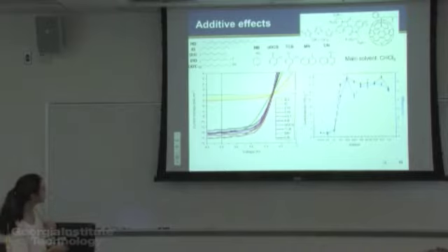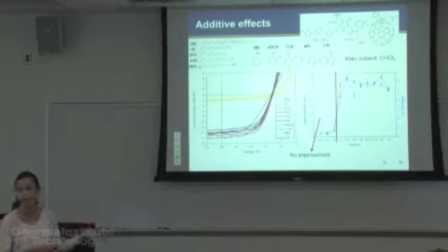And so what's interesting is that, again, very little change on the open circuit voltage, but drastic change in the short circuit currents, and we can outline two different domains for these processing additives. One where we see no improvement compared to the pure solvent chloroform, and then one where we can see an increase in the short circuit current.